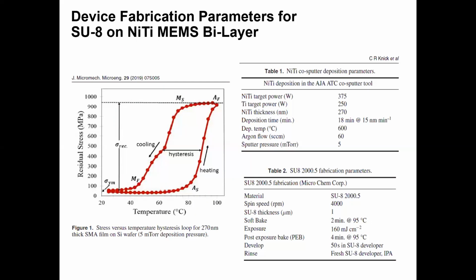And then this slide highlights some of those device fabrication parameters used to build the MEMS bilayer actuator based on SU8 and NiTi. Figure 1 shows the stress temperature loop for the SMA device wafer, exhibiting over 800 megapascals of recovery stress, which is a desired parameter for large deflections during the phase change.